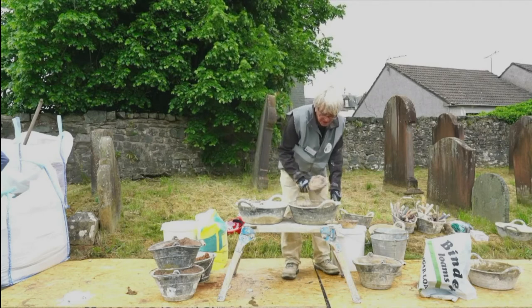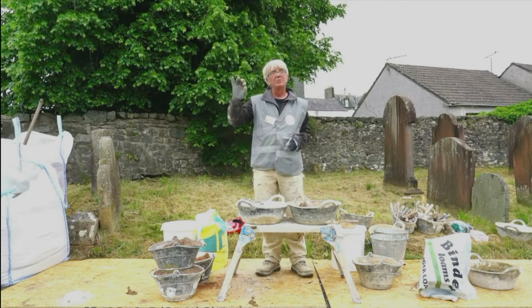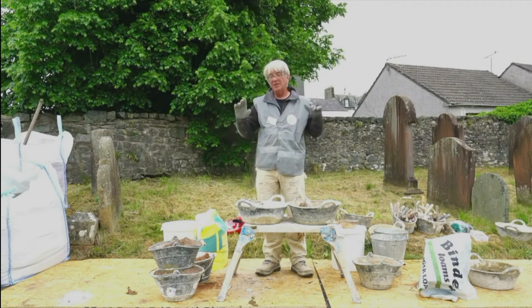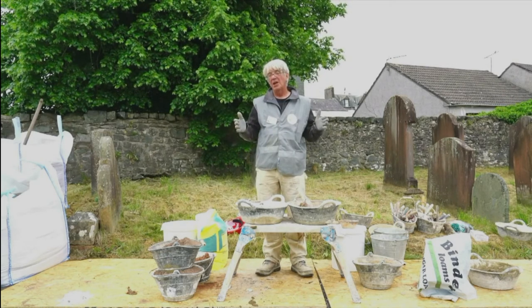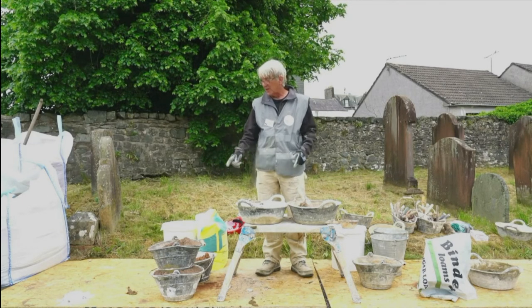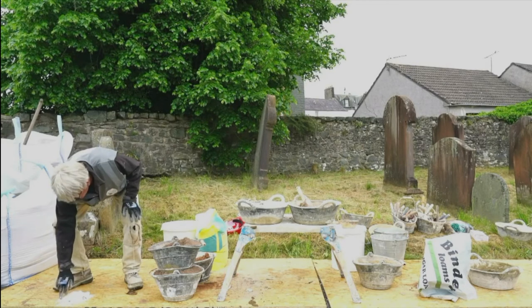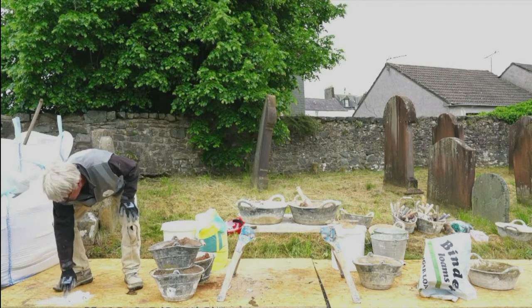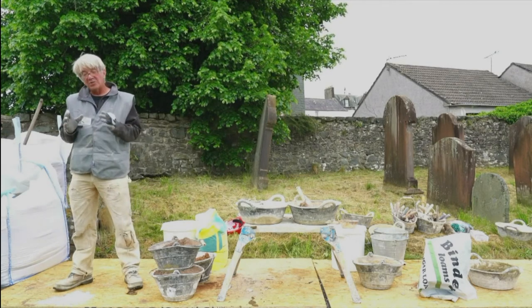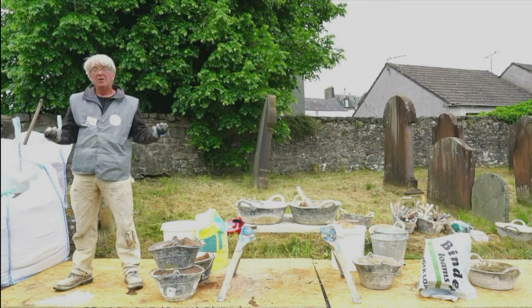And the lime lumps, I haven't mentioned that, but when you look at an old mortar and you see little lumps of lime, they could be any size depending on the size of the joints and so on, that's a fairly solid reason to say they were hot mixed from quicklime. That's because what we'll get in here, and we've got some here, is some of this lime which is slightly underburned, and some that's slightly overburned. That won't necessarily slake as well, so those will be the lumps. They're either underburned lime or overburned lime, which hasn't slaked because of that.